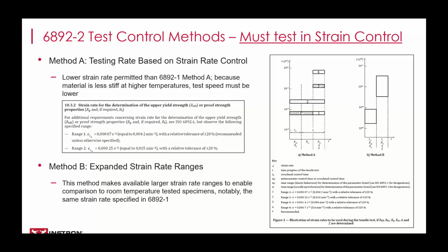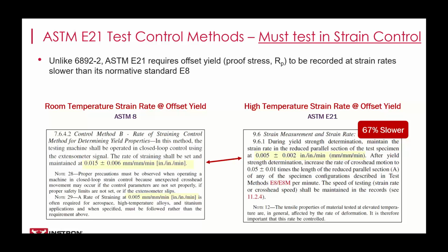The second method is not as commonly used in production environments, but because it uses the same strain rate as 6892-1, it enables direct comparison between the alloy at elevated and ambient temperatures. So we see this in academic and research centers quite often, but again, less common in production testing to qualify parts. Now, ASTM E21 takes a different approach in describing these methods. Unlike 6892, instead of the ranges existing in the elevated standard, instead they're specified in the ambient temperature standard with the slower rate corresponding to aerospace alloys at ambient temperature and all alloys at elevated temperatures.